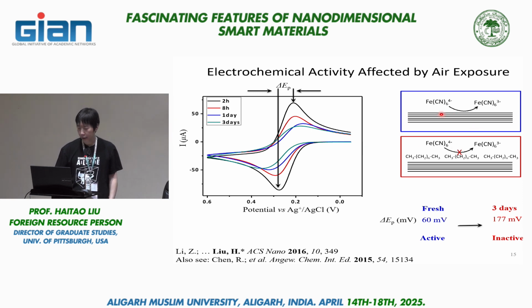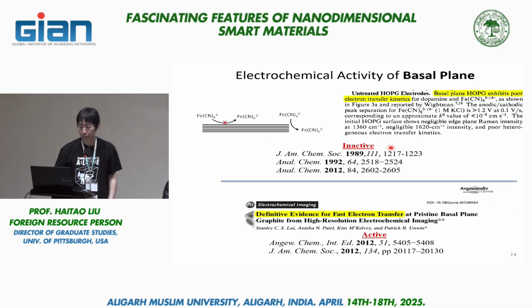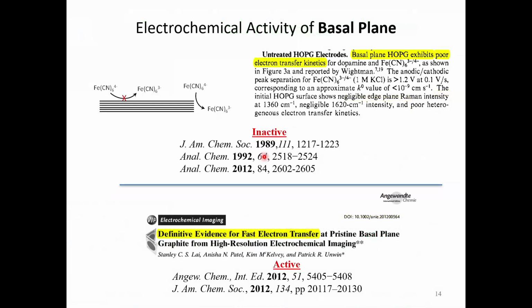Now, if you go back and look at those two very different conclusions, you may guess that, in the case of McCreery's work in the 1980s, they were probably working with contaminated graphite. And indeed, we think that is the case. We dug into their experimental section, and we found that they used a particular technique to define the surface area of their electrode. The way they did that was to cover the surface they did not want to measure with paraffin oil.